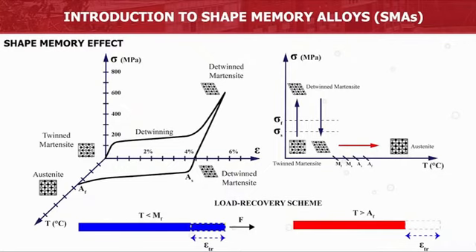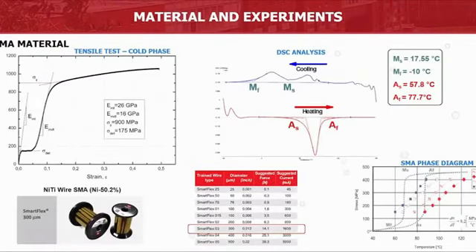The main property is the shape memory effect, that is, the capability of the material to recover a pre-strain that can be imposed during the cold phase under the martensite finish temperature. Then the material, when heated above the austenite finish temperature, will fully recover the pre-strain impressed in the cold phase. The material chosen in this study is an NiTi wire with a diameter of 0.3 from the SmartFlex producer, and all the data was obtained from the datasheet of the material and also through some experimental tests made in our laboratory.